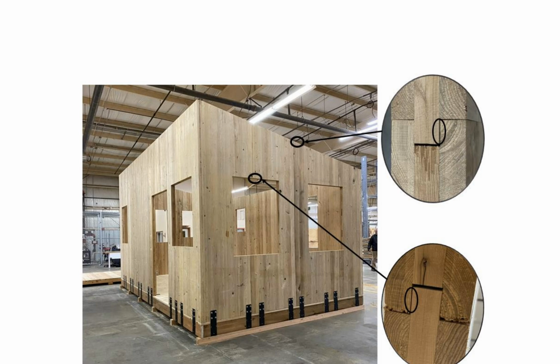The study presents a demonstration structure featuring thermally modified CWH cross-laminated timber (CLT) panels with a tight 1 mm clearance between the side faces of the tongue and groove (T&G) joint to ensure precise panel alignment. The findings provide useful design guidelines for accounting for the effects of thermal modification on the mechanical behavior of CWH and contribute to the development of rich databases for calibrating and validating computational design tools.